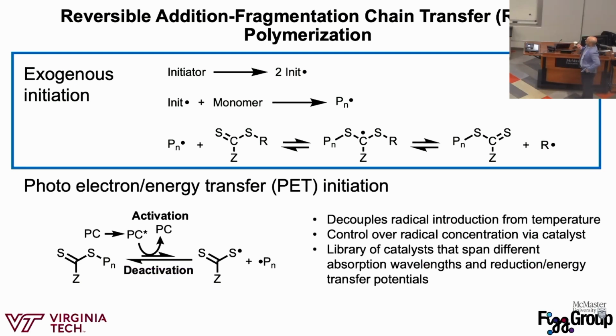So in exogenous initiation, this could be some sort of azo initiator, where you're relying on heat to degrade that azo initiator to introduce radicals into the solution. You're always going to have some amount of chain ends that were started from that thermal initiator, so you get a lower purity of polymer chains, let's say.